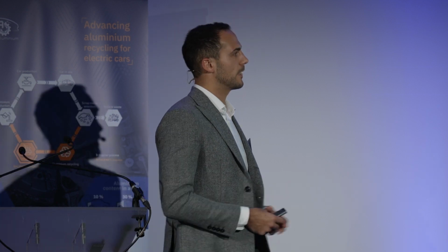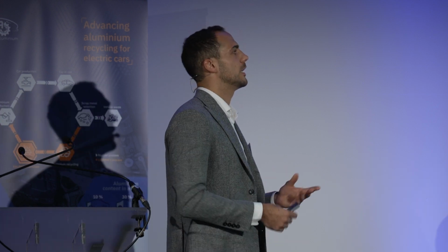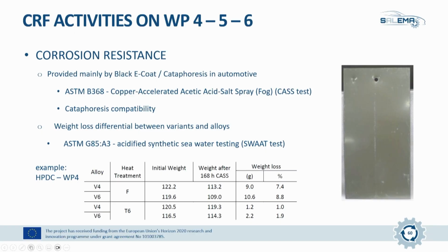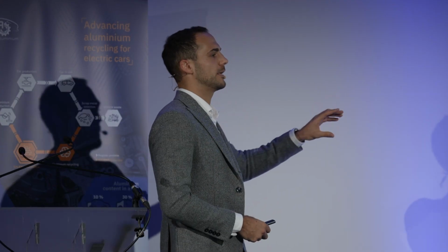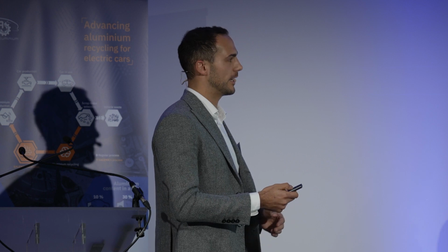Then we did something at more laboratory scale, the weight loss differential, to see how much these alloys corrode. This is just an example of the casting part. Since I didn't specify, I'm doing my PhD on high pressure die casting, so I specialize more in that. We can see some slight differences between, for example, variant 4 and variant 6, and also some difference in corrosion after the heat treatment. Obviously, these components will never be without cataphoresis in a car, but it's interesting to see how they behave.